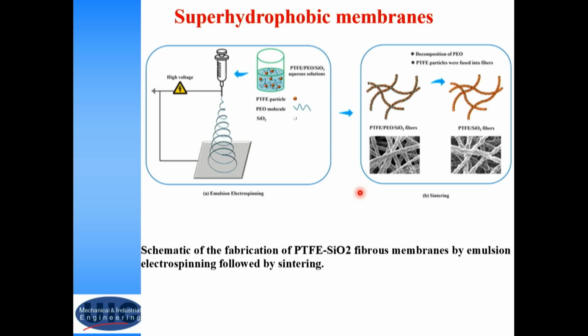So when you do this type of electrospinning, after all, you end up with fibers which you can try to sinter. And when you sinter them, you eliminate PEO completely, which is unneeded. It's just like a plasticizer, essentially, during the process. Whereas you sinter glass beads, and you have Teflon covering everything, and the beads providing roughness. So the idea, as I told you, is waterproofness, and some other additional properties, and I'll tell you this step by step. So this is an overall approach which starts with electrospinning and goes that way.